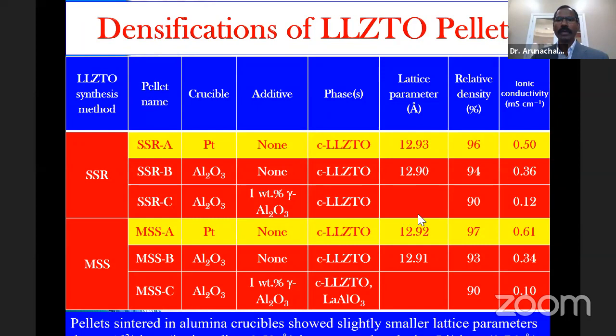This table also gives you the lattice parameter. As you can see, all three different types of pellets are from the powder made by the solid-state reaction, and similarly by the molten salt method: sintered in platinum crucible, sintered in alumina crucible without any additive, and alumina crucible along with 1 weight percent gamma alumina as a sintering aid. The pellets sintered in platinum crucibles both led to lattice parameters almost the same, 12.91. So it's certainly the cubic phase and no other impurity phases.